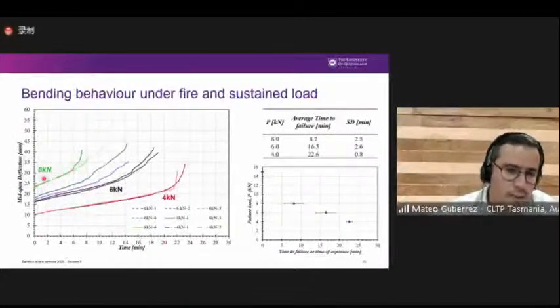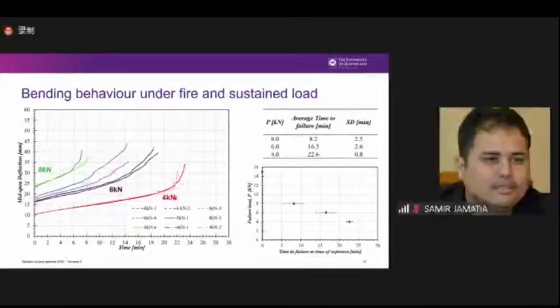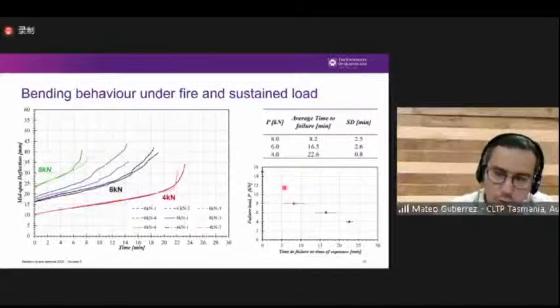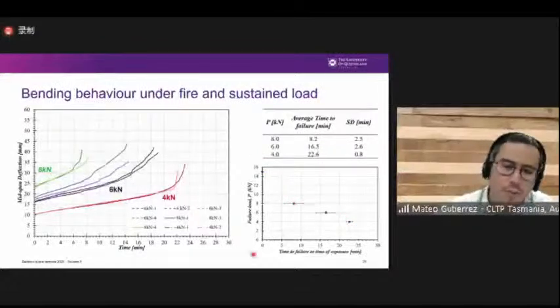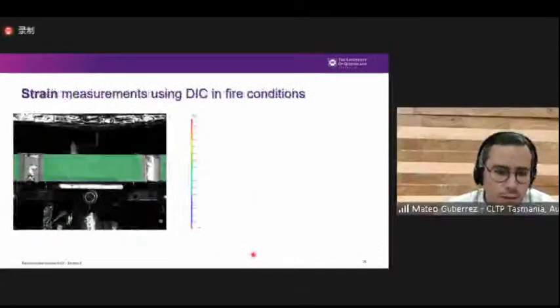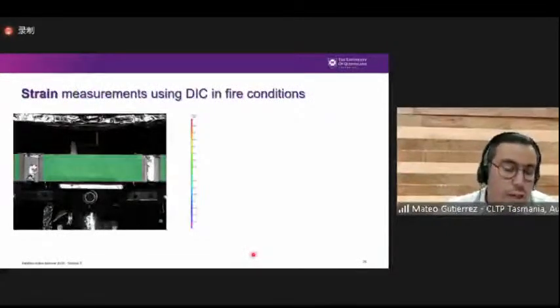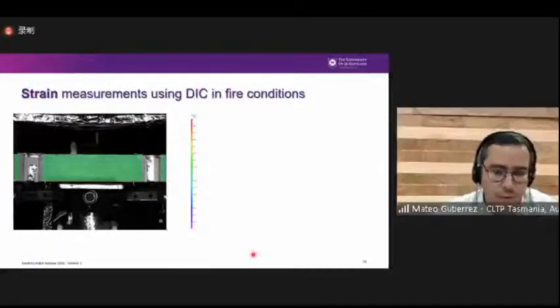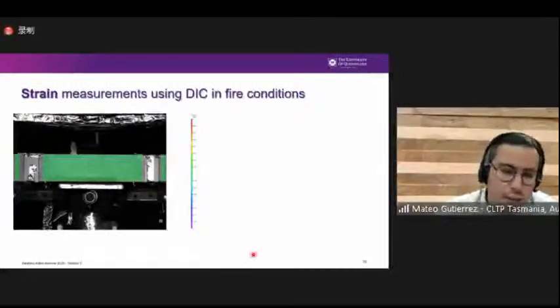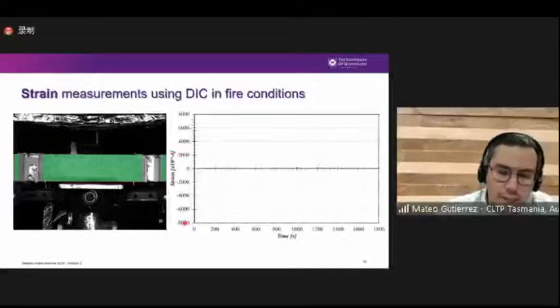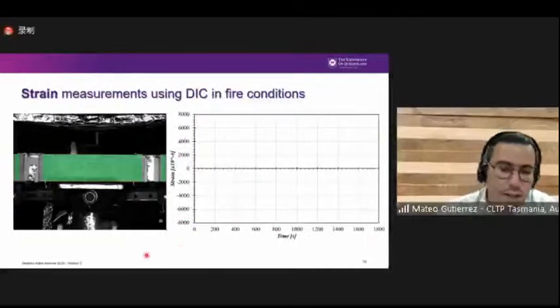These were the beams tested at 8 kilonewtons. These were the beams tested at 6 kilonewtons, and these were the beams tested at 4 kilonewtons. And then we also obtained the reduction in the load bearing capacity against time of exposure. But we not only measure the deflection, we also measure strain, which is quite a difficult property to measure in a fire test because of the smoke production and the conditions of the fire testing. But thanks to the use of DIC, we were able to measure strain against time, but also against load.